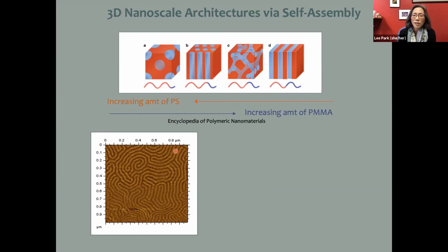And you can sort of get a sense of that. What you can understand is that you're getting these very regular features, right? You're getting these very regular stripes. They're very uniform in size. The individual stripes, the light and the dark, are the red versus the blue polymers, all right? So you're getting this very interesting organization. It's kind of beautiful. The thickness of these stripes is on the order of tens and hundreds of nanometers, so very small features. So you can take this kind of system and you can now play more games with this.